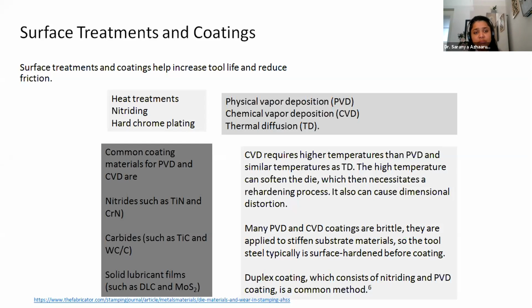And what kind of common coating materials do we use in PVD and CVD? Generally, nitrides and carbides. They are the best form that you can see in PVD and CVD coated substrates, like titanium nitride, chromium nitride, titanium carbide, or tungsten carbide. I was working in my PhD mostly on chromium nitride and titanium nitride coatings for non-stick applications. They are very good in forming very thin coatings, and they have a very good resistant, wear coating layer, and this is very clear why it is used in many applications. And solid lubricant films such as DLC and MoS2 are also very popular.